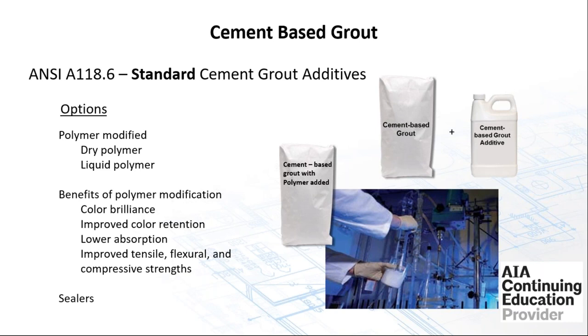Polymer modified. You have a dry polymer or a liquid polymer. Benefits of a polymer modification, in other words, adding a polymer to the mix: color brilliance, improved color retention, lower absorption, improved tensile, flexural, and compressive strength. It just makes it an all-around better mix. Again, making it denser, making it more flexible, less susceptible to staining. And you have two types. You have a dry polymer, which is generally factory blended, and it comes in the bag itself, and you mix with water. Or you have a liquid polymer, which is a lot of times used in lieu of water. So a couple different types. Again, they're both very effective. This type of grout, although it's not absolutely required, it's definitely recommended to have a sealer, especially in a high traffic application or installation.